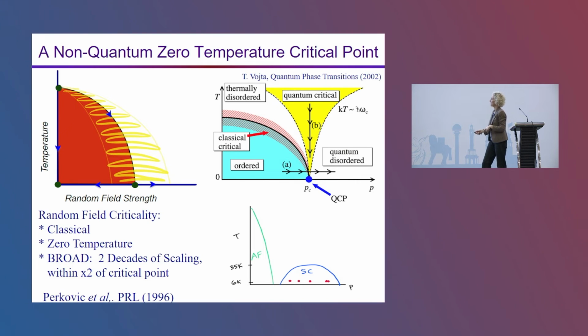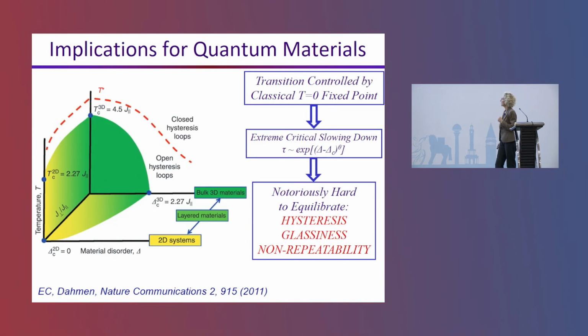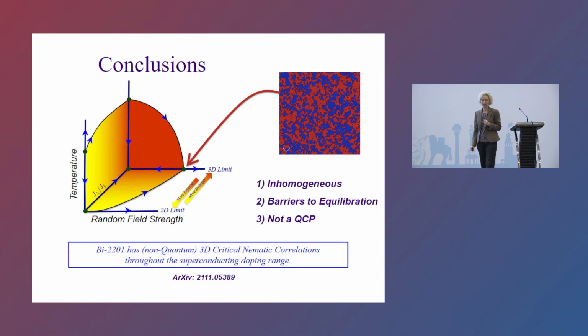It's not like quantum criticality, but it is like random field criticality, which is a classical zero temperature criticality. It just has a much, much broader critical region. So the critical region here in a random field model is huge. Like I said, you can get 2 decades of scaling within a factor of 2 of the critical point. So I claim that this looks much more like this case. It's not quantum criticality because it's a very broad critical region. And I will leave you with those ideas, and thank you for your attention.